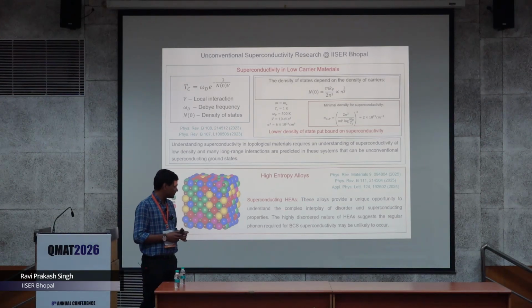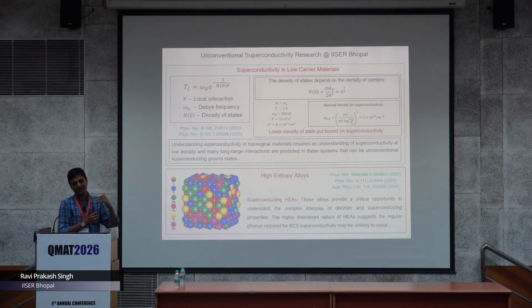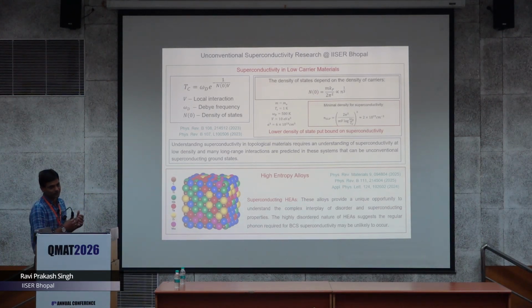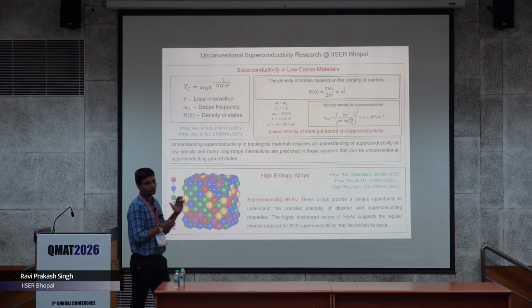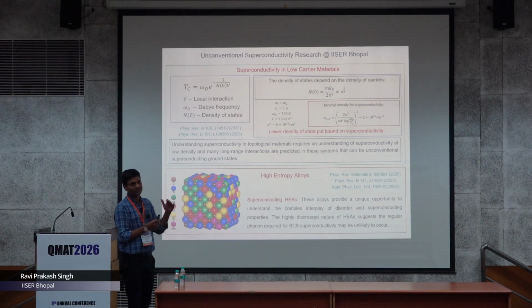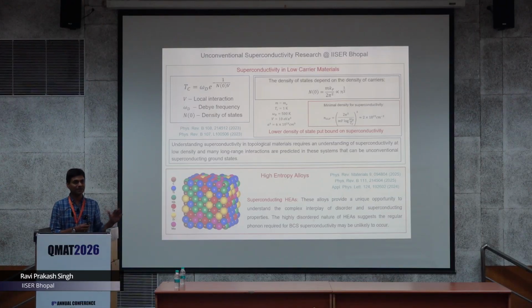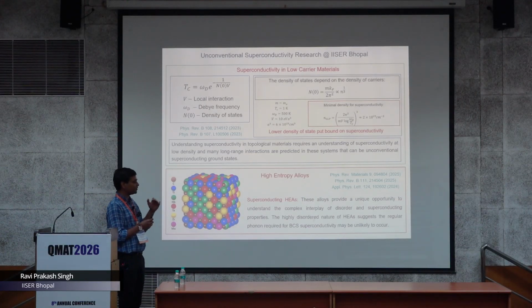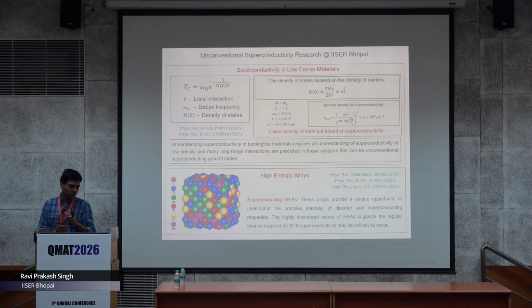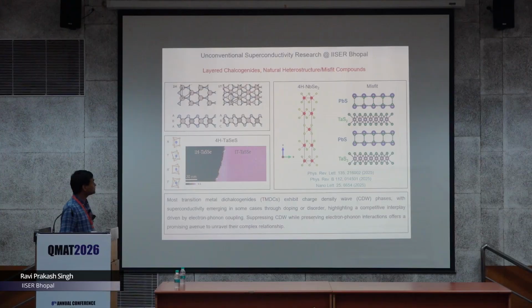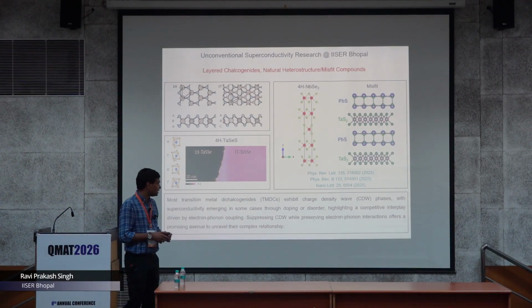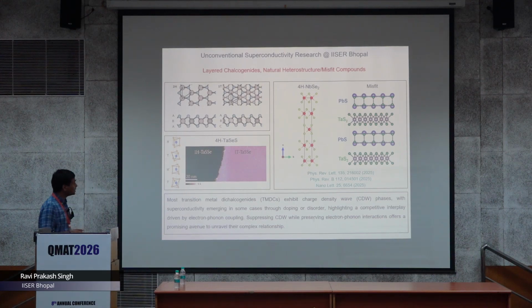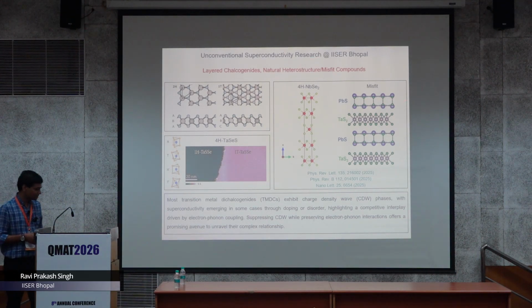And surprisingly, we found that even if you have different elements present with different molecular weight, we are getting proper phonon mediated superconductivity. So it is still a puzzle how we are getting phonon mediated superconductivity, and it is very robust superconductivity in these high entropy alloys. So now, recently we started working on these layered chalcogenides and natural heterostructures.